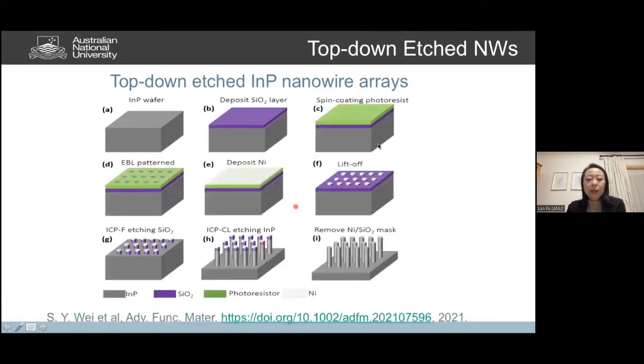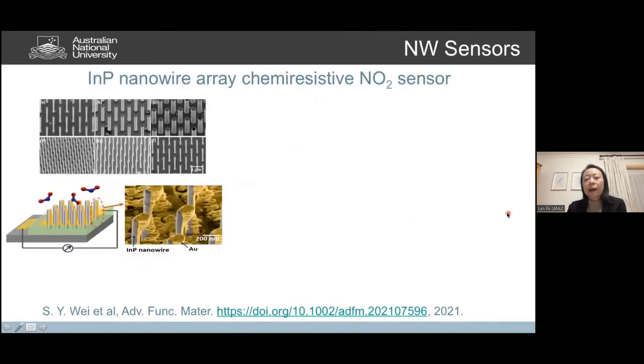So for how we fabricated top-down, basically we use a series of masking techniques, using silicon dioxide and nickel as mask, and using ICP etching to do the top-down etching and create an indium phosphide nanowire array. So here again, we are using just a pure indium phosphide substrate to create different devices. This device is an undoped indium phosphide substrate.